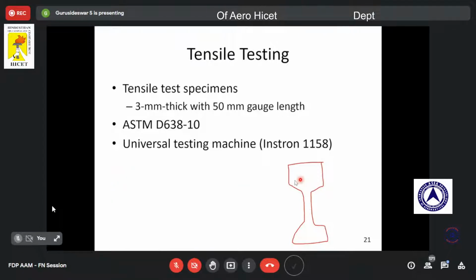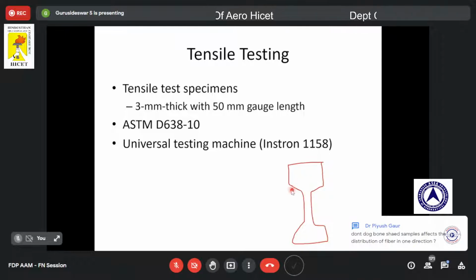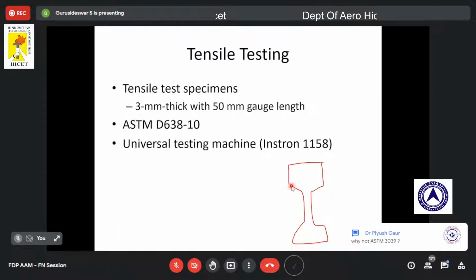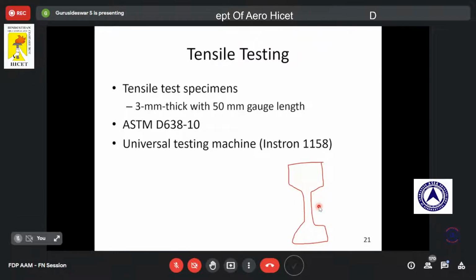The purpose of having a larger area is to avoid stress concentration, because this grip area will be rigidly fixed in the tensile test. So in order to avoid grip failure, we have a higher surface area, and also if you have a sharp corner, then this will lead to stress concentration. That's why we go for this curvature, so that we can expect the failure to happen at the gauge length, so that I will get accurate results. So that's why we go for a dog bone shaped sample.